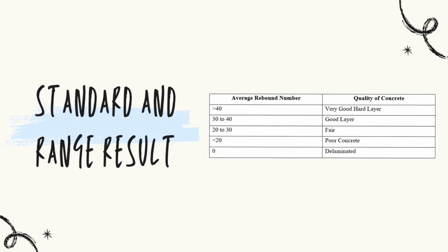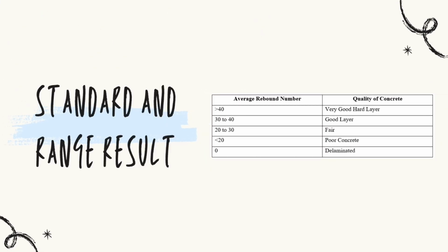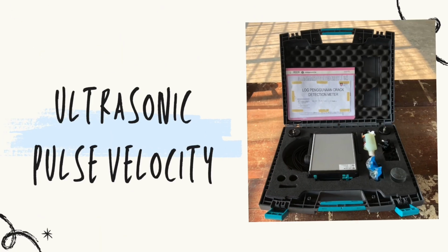Standard and range of result. According to the standard, data above 40 N/mm² is a very good hard layer concrete. 30 to 40 N/mm² is a good layer concrete. 20 to 30 is fair. Below 20 is a poor concrete, and lastly 0 is delaminated. We move to the next equipment.